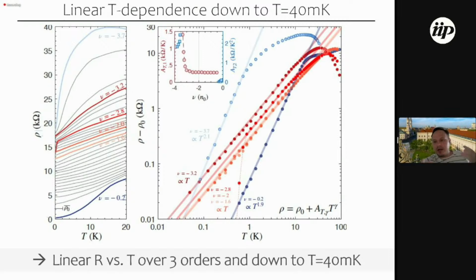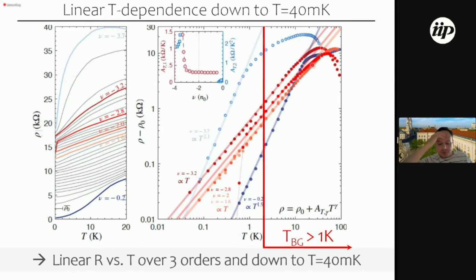So over 3 orders of magnitude, we have here a linear temperature dependence which penetrates all the way down. And really, what is the most striking point that we want to mention here is that if you would estimate the carrier density and the Bloch-Grüneisen temperature, which we would obtain from the Hall density here, then the Bloch-Grüneisen temperature for all these curves would be way above 1 Kelvin. So in principle, from an electron-phonon picture, you would only expect the high temperature regime to be linear, but you would not expect the low temperature regime to behave in such a way.